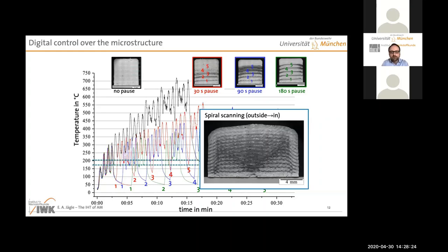You can start playing with other scanning strategies. In this case, it was a spiral. So you have a very funny precipitation, and therefore hardness map, inside your material. You can think about doing a lot of different things with these two different switches that you have available for martensite and for precipitation.